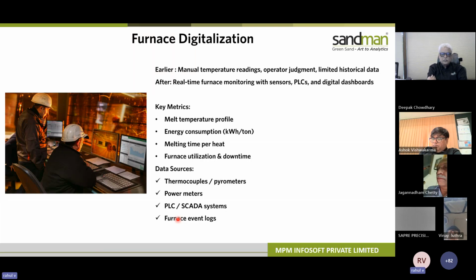Yes, so the melt temperature profile will give you the exact temperature of the metal, of the melt that we are handling, across space and time. So this gives an idea. Let's take, if the temperature of the melt is low, the fluidity of the metal will be low. This creates misruns, cold shuts, and incomplete fillings. On the other hand, higher temperature will cause us oxidation, gas pickup, and metal penetration.